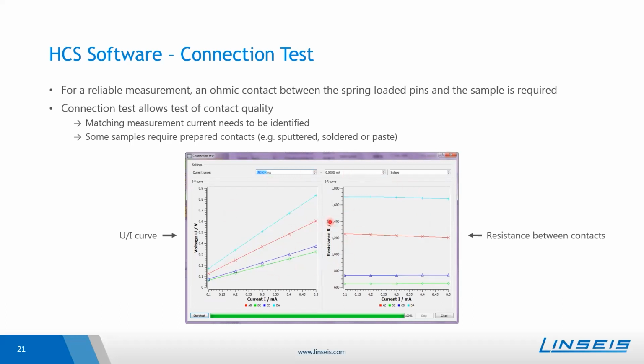If those curves do not show the ideal behavior, one can try to prepare the contacts or modify them a little bit. For example, you can sputter some gold edges onto the sample or solder contacts, or use, for example, a silver paste just to have maybe an improved contact. After that, you can try this connection test again until you have an ohmic contact between the pins and the sample itself.